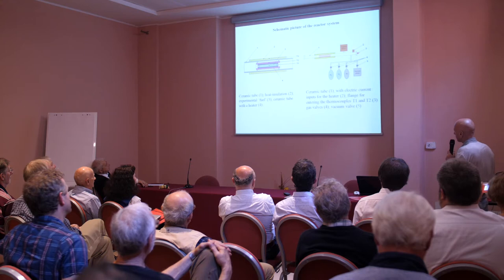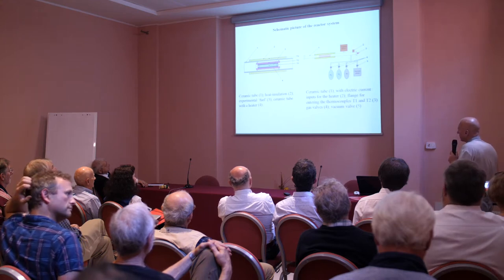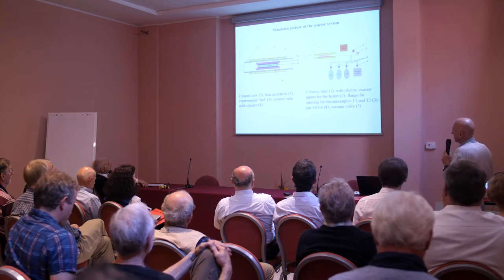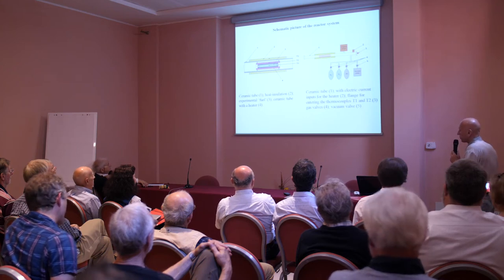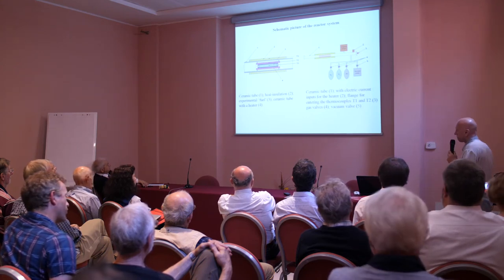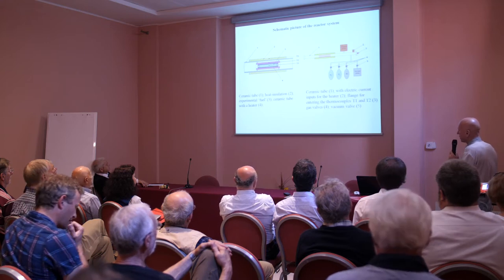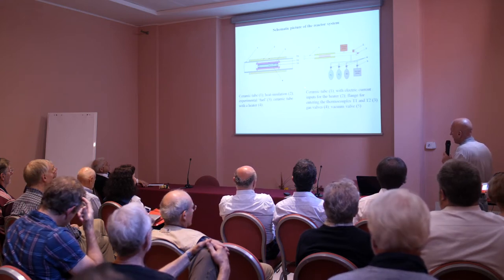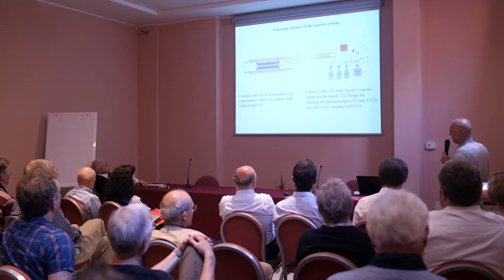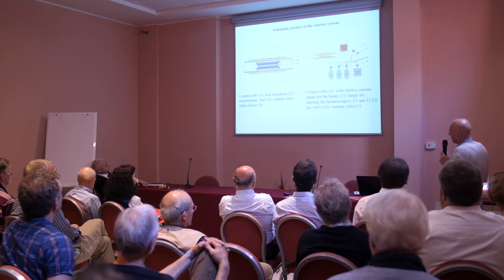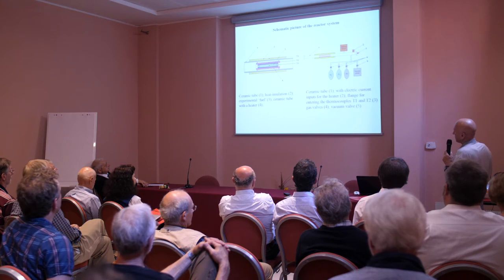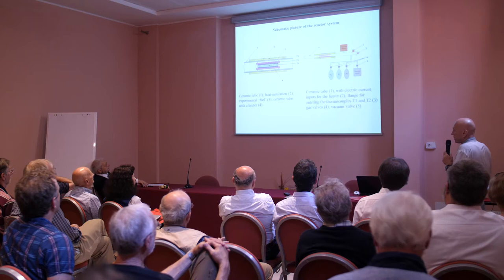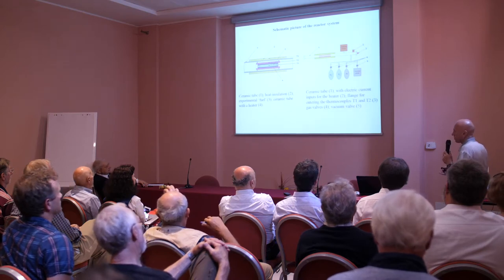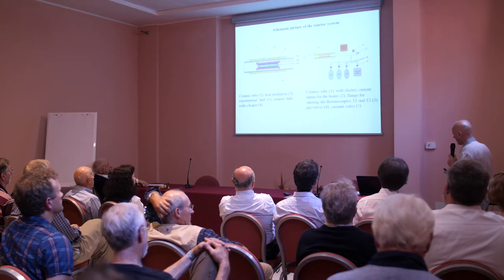We also make a more or less good vacuum system. And the idea is, first of all, that when you do just calorimetry, you just play with some output, input numbers. But when you measure these two temperatures, and if you see that the temperature inside the fuel is higher than the temperature directly at the heater, the only reason behind that could be the production of some extra heat. That's the idea.